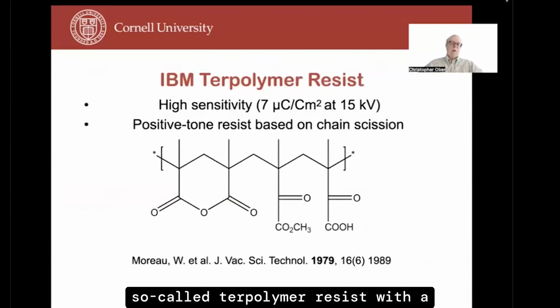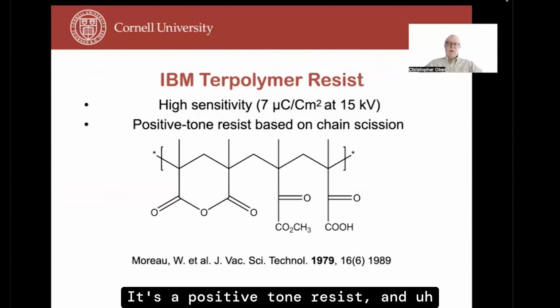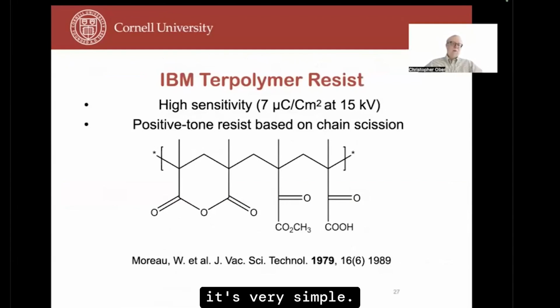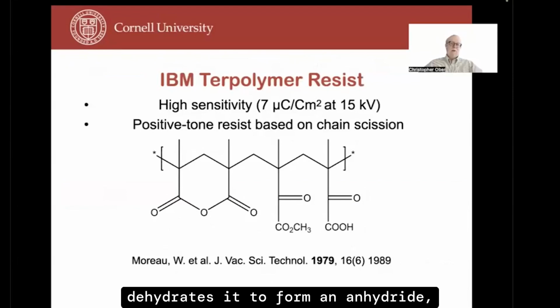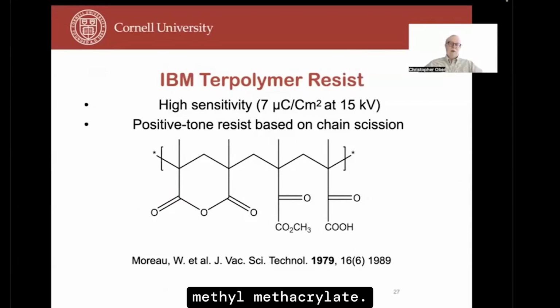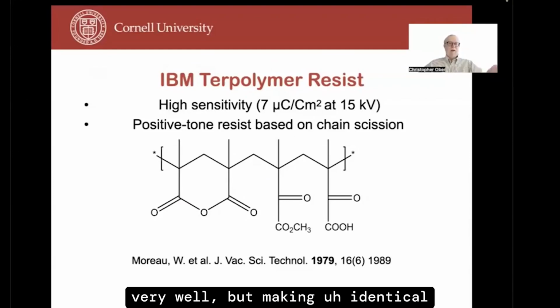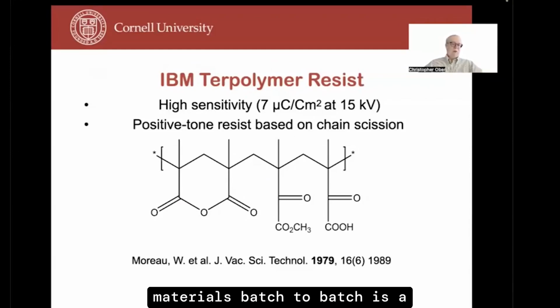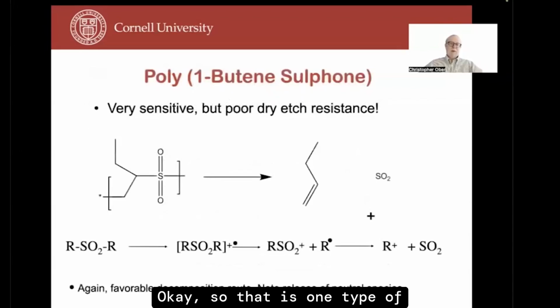IBM also patented many years ago a so-called terpolymer resist with a sensitivity below 10 microcoulombs. It's a positive tone resist, and it's very simple. It just takes maleic acid, dehydrates it to form an anhydride, and also has some content of methyl methacrylate. And so this system works very well, but making identical materials batch to batch is a challenge. Okay, so that is one type of scissionable resist.